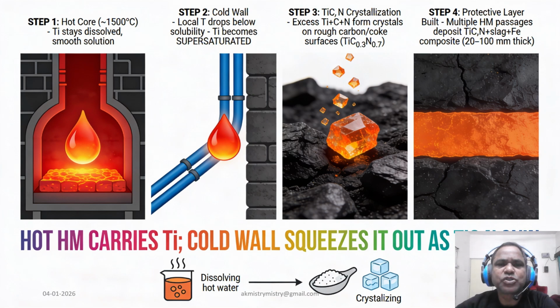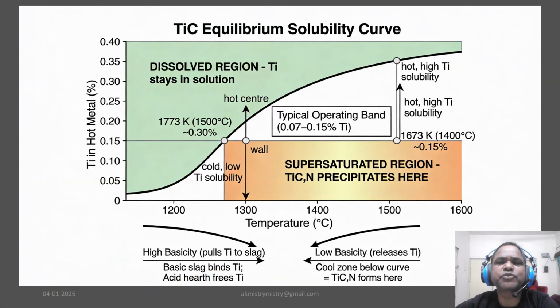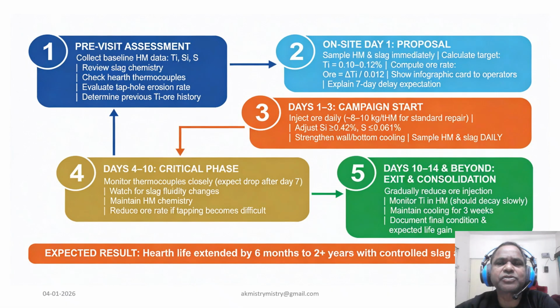The TiC equilibrium solubility curve illustrates why temperature control is our primary lever. In the dissolved region at high temperature, titanium stays in solution very comfortably. As we move into the supersaturated region, by cooling the metal near the wall, TiCN is forced to precipitate. One thing we must remember: high basicity pulls Ti to the slag, while low basicity releases Ti to form the protective layer that we have just discussed in the earlier slide.